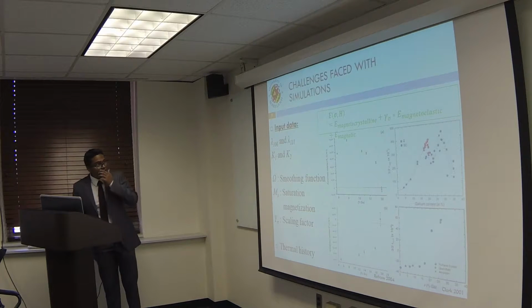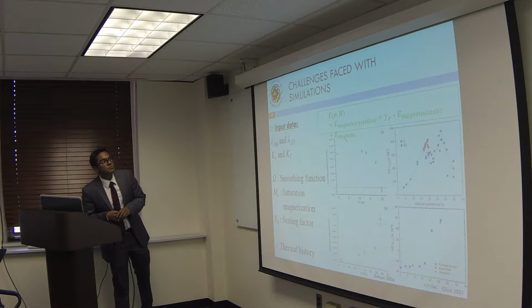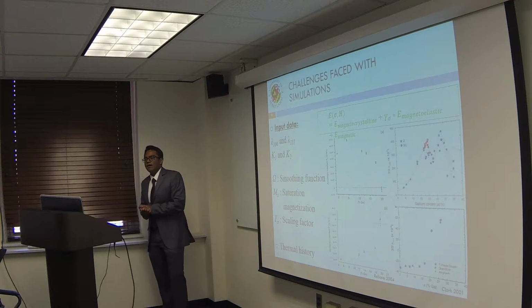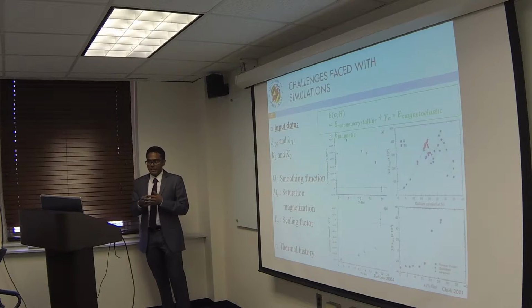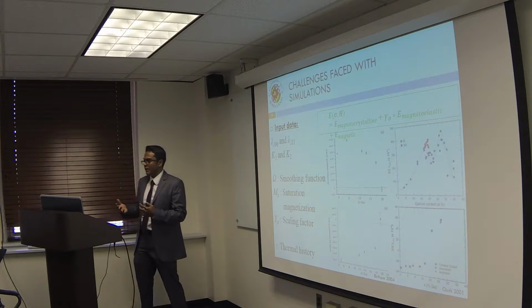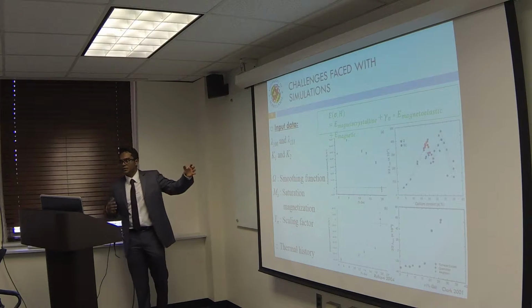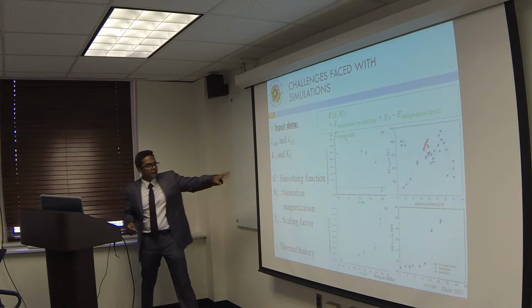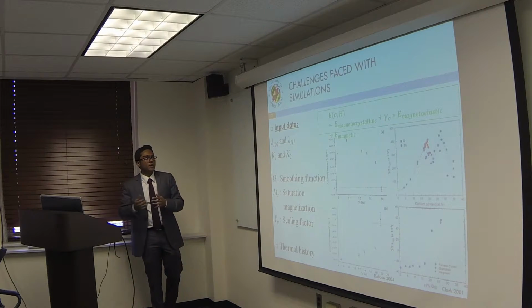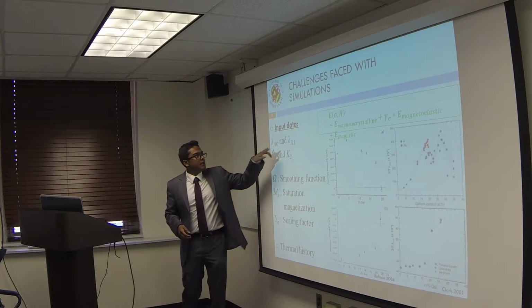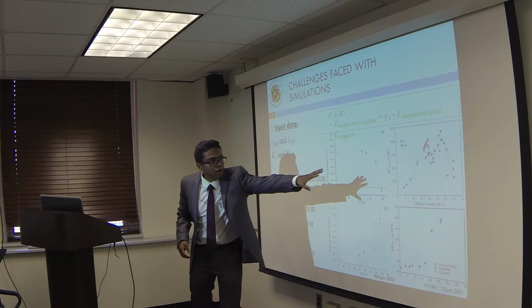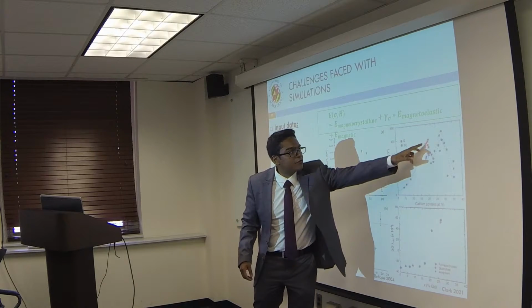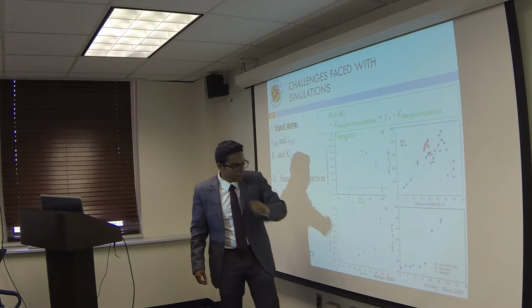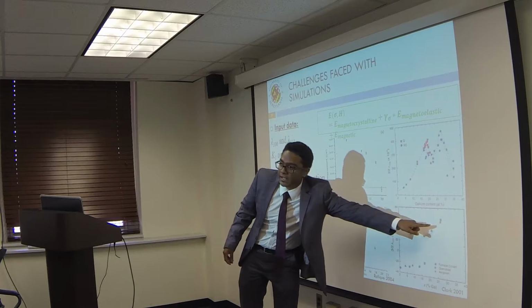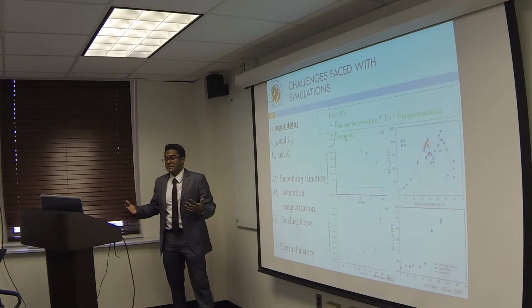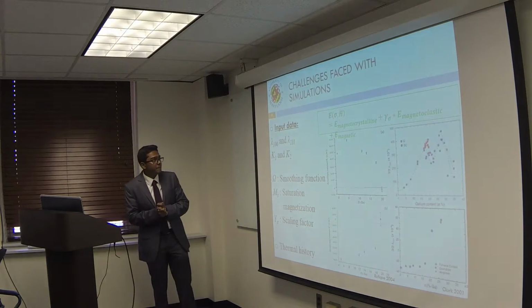So we faced a few challenges when it came to the simulations, because the simulation was very dependent on the input data that goes into it. We had 7 major inputs that we had to give to the simulation. As you can tell, for lambda 100 and lambda 111, we did not have some values for the quench samples. And for lambda 111, we only had 1 data point for the quench samples, and all my samples were quenched to increase magnetostriction.